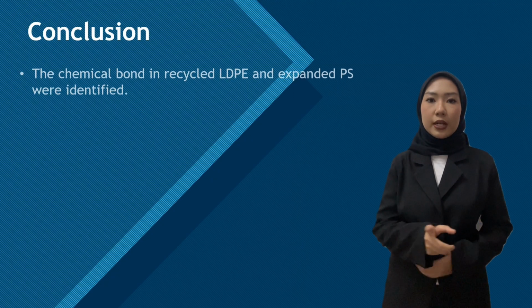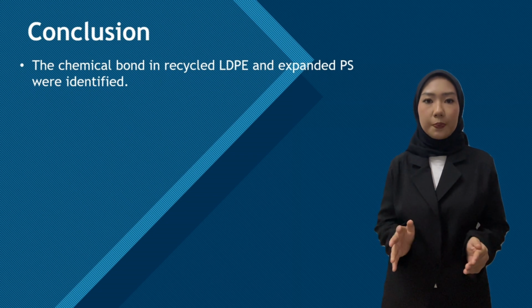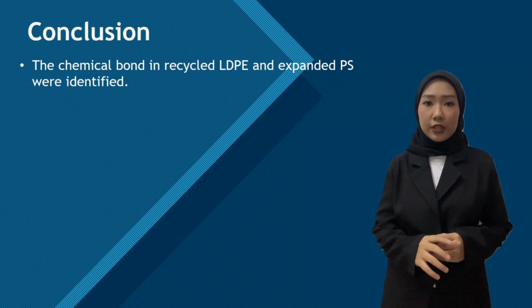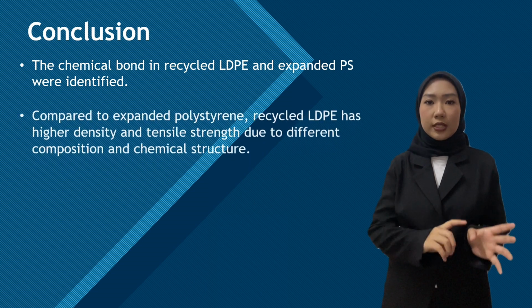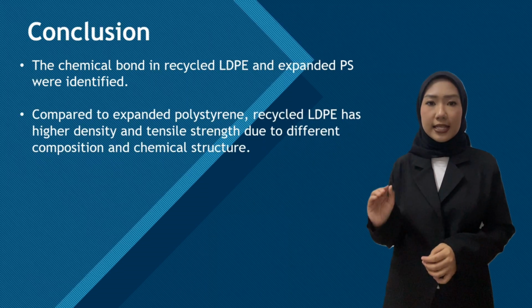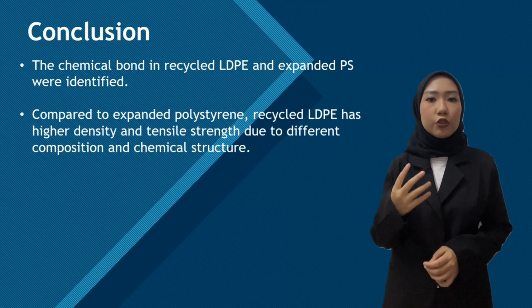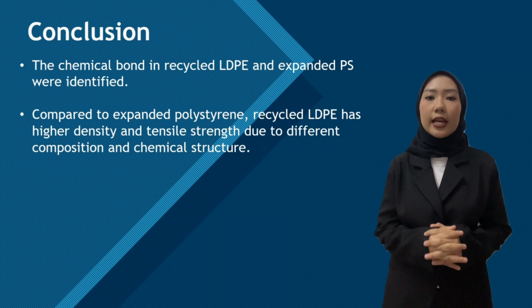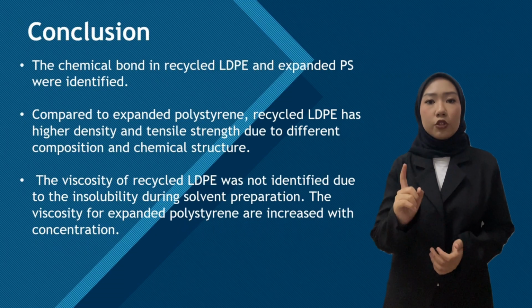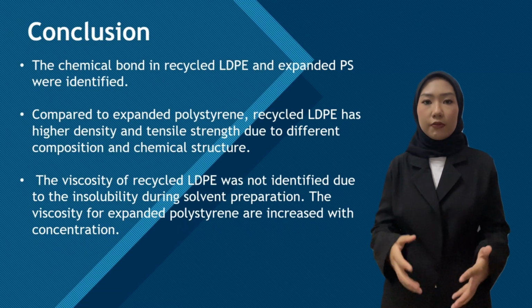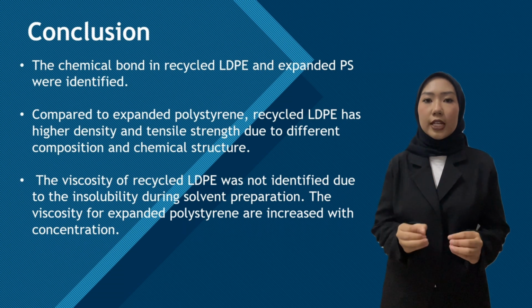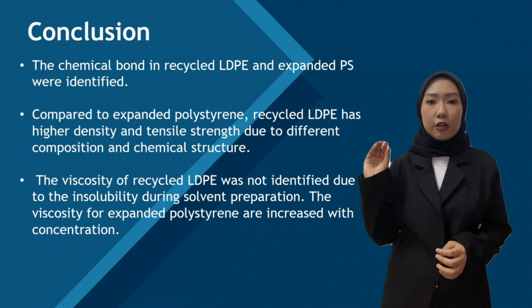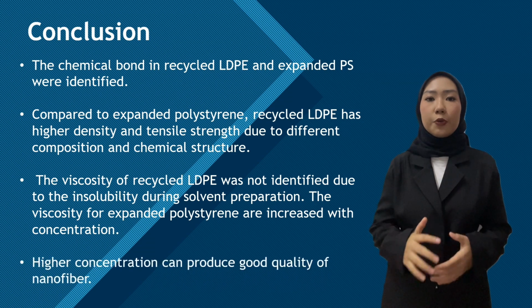concentration is reached. To conclude this research, the chemical bonds in recycled LDPE and expanded PS were identified through FTIR. Compared to expanded polystyrene, recycled LDPE has higher density and tensile strength due to the different composition and chemical structure. The viscosity of recycled LDPE was not identified due to the insolubility during solvent preparation. The viscosity of expanded polystyrene increased with concentration. Higher concentration can produce good quality of nanofiber.